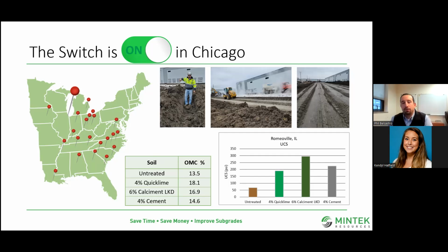This customer, I'm not sure if he's on, but hey, he's been using quicklime here for some time now. And here we are confidently hitting our 150 PSI mark at 7 days, but really we were close to the 200 mark and growing with time. Also, once again, benefited from soil modification. You can see the untreated optimum moisture content at 13.5. So he had to dry that soil back to that almost 14% mark. If we didn't throw anything in it, cement increased that a bit to 15-ish, but the lime products almost 17, a little over 18. So we didn't have to dry it back as much to hit that target mark.